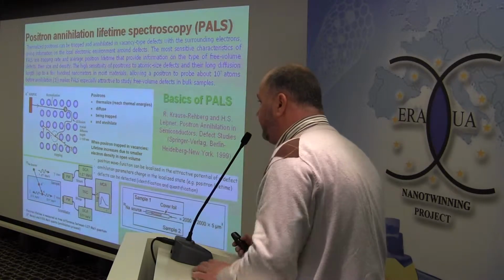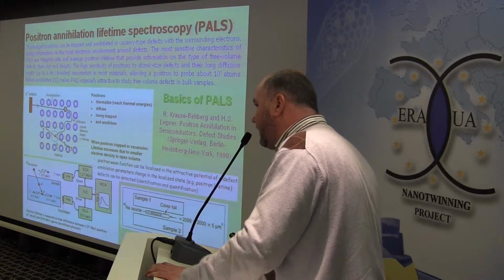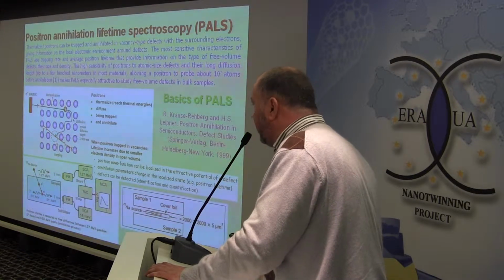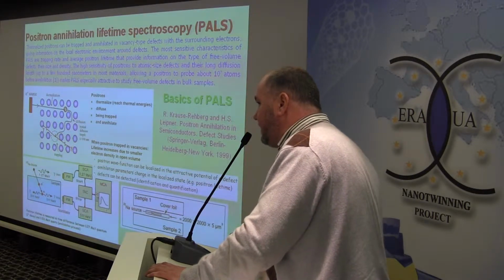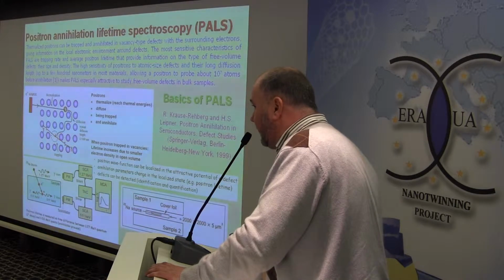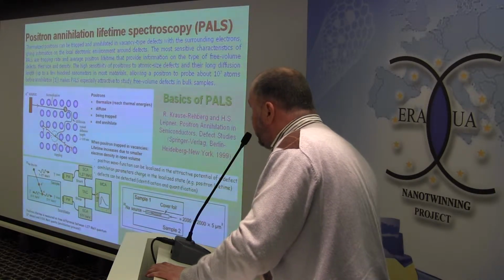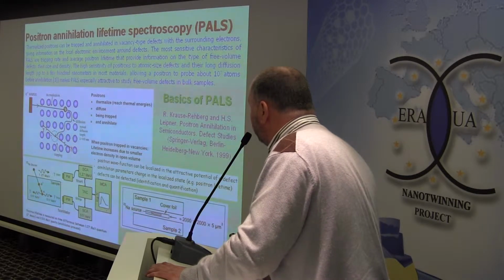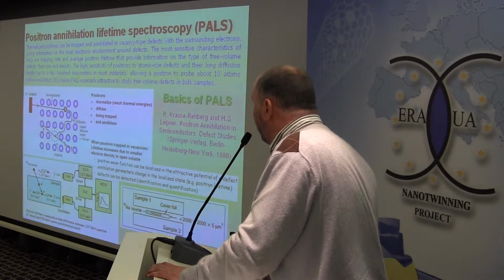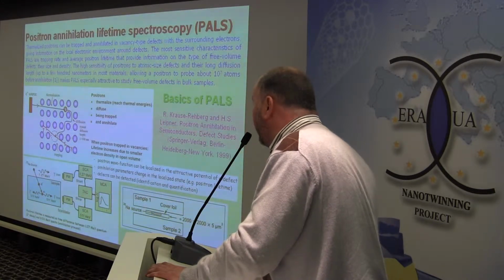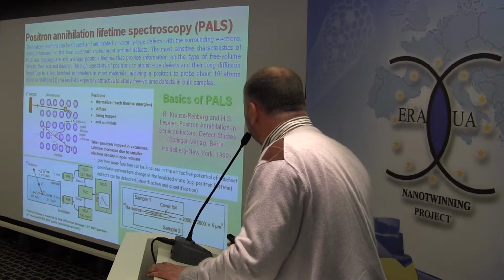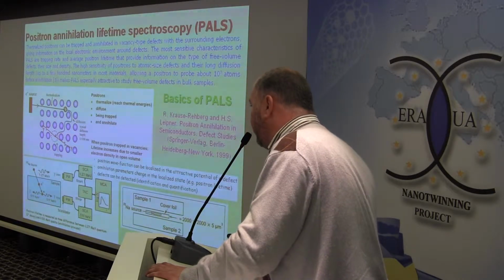We also use, for the first time, positron annihilation spectroscopy techniques to investigate carbonization processes in ion-implanted polymeric materials. One of these methods is positron annihilation lifetime spectroscopy. The thermalized positrons can be trapped and annihilated in vacancy-type defects, giving information about the environment around defects and free volume.